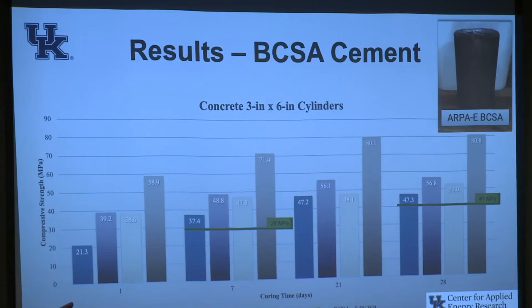We're currently investigating what we call hybrid cement, different combinations, picking out the best components of what industry knows are the best phases for performance and durability. But what you get with this is a very dense system. Strength is not a marker of great durability over time, but what helps is the density of the material and its ability to prevent the external world from getting into the rebar, the steel embedded in it. Once steel sees any form of hydration or chlorides, it's going to rust, expand, crack, and so forth. So this provides a very dense system that was very resistant to anything externally penetrating it to break it apart.